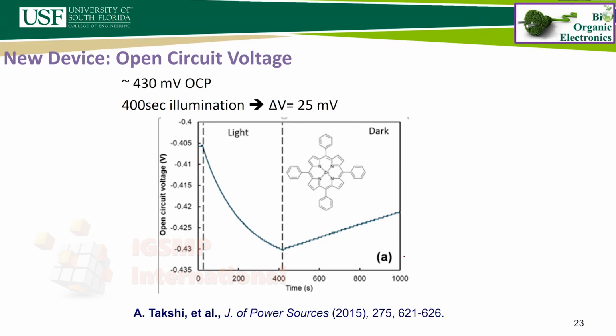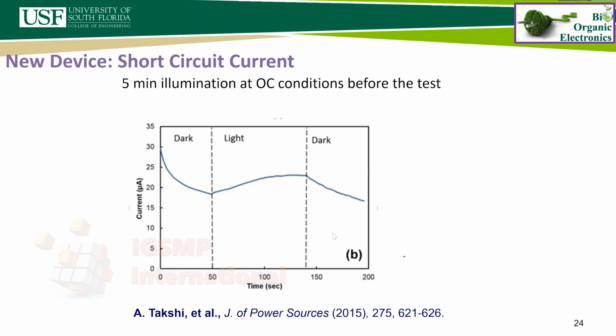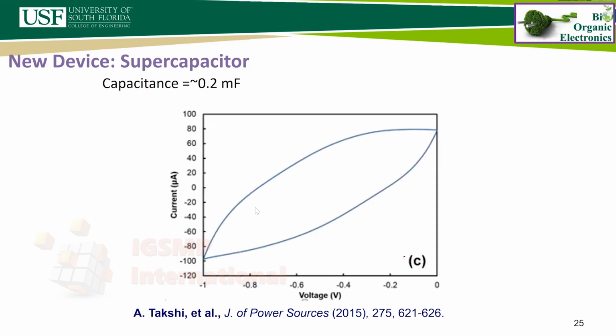And it wasn't an instantaneous increase of the voltage, but it was very gradual, which implies that there was some actual storage effect inside of that. And more interestingly, when we stopped shining the light, the voltage stayed at a higher level, which means that there's still some energy stored inside the cell. The short circuit current also showed some advantage, in that even in the dark, you can get some current out of the cell. And testing it as a supercapacitor with cyclic voltammetry, the device showed a very decent amount of capacitance for a cell like that.